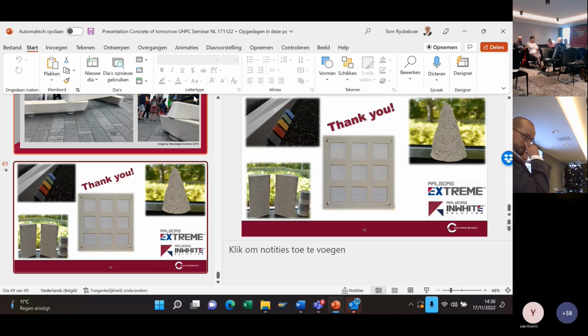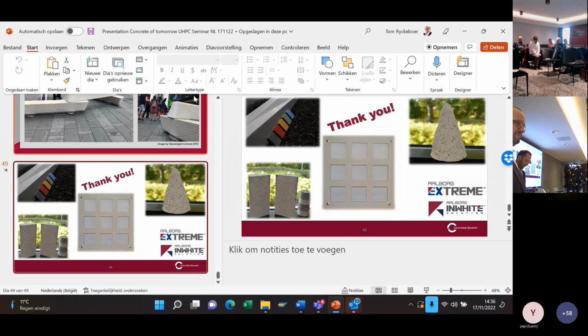And you have to measure it actually from the moment that you are casting, when you want to have a really accurate figure, especially for UHPC, because there you have the largest shrinkage in the first few hours. So when you cast a mold, you let it harden, bring it to the lab, and start to measure it, it's already wrong. Yes, I only know it's measured according to the standards, and then of course, discussion can indeed be whether the standards should be changed. It's very important for prefab, because you have balls and other things in it. So in the traditional UHPC, you talk about several millimeters per meter, so that's already enough to make a crack.